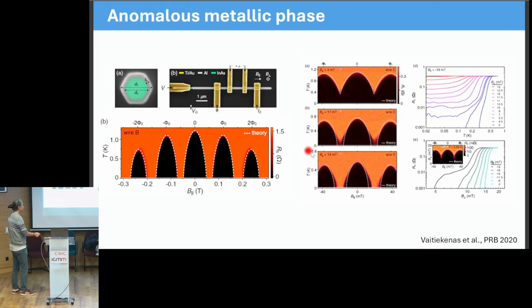And in this work, in particular, what they see is that by tuning this superconductor with the magnetic flux, they observe some kind of transition in which this hybrid structure can be in the normal state when applying magnetic flux, fully suppressing the superconductivity of the shell. It can be superconducting when we have an integer number of magnetic flux quanta, but also in some conditions they observe some behavior in which the superconducting transition starts, but the resistance doesn't go to zero and saturates to a finite value. This is also a phenomenon that is seen in other systems and is known as an anomalous metallic phase, right? So this is one of the works on these wires.